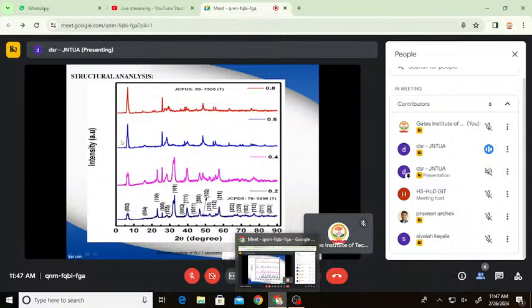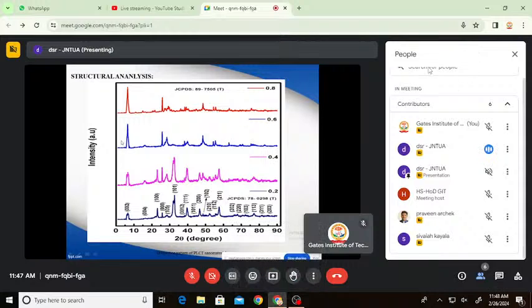The unit cell volume was found to be reducing as a function of substituent concentration. This may be due to decrease in lattice constant with increment in Z value. The mean crystallite size D was found by Debye method. And the mean crystallite size was noticed to be varying from 10.50 to 15.50 nanometers. The crystallite size varied randomly as a function of lanthanum content.